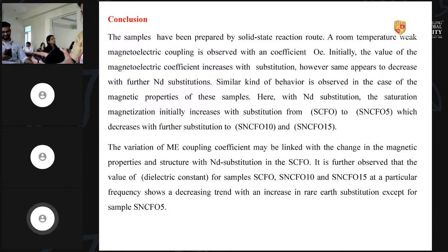It is further observed that the value of the dielectric constant for samples SCFO, SNCFO10 and SNCFO15 at a particular frequency shows a decreasing trend with an increase in the rare earth substitution, except for the sample SNCFO5. These are the references.